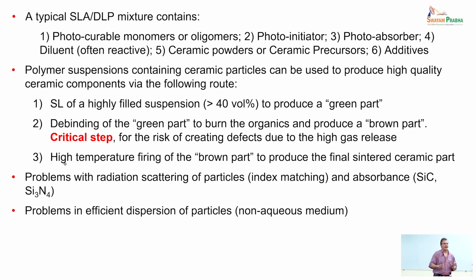In any case, independently of how much powder you have and what kind of technology you're using for shaping your powder, in the end you have a green part. You have your shaped body, looks nice, has the strength that you need for further handling, but the further handling requires first debinding, the burnout of the polymeric part, and then sintering. And if you're familiar with conventional ceramic processing, you know that, for instance, injection molding or other extrusion-based technologies often use some polymers as binders for ceramic processing. But in those cases, the content of organics is much lower. Here, you have at least a minimum 40 volume percent of a polymer that needs to be eliminated.